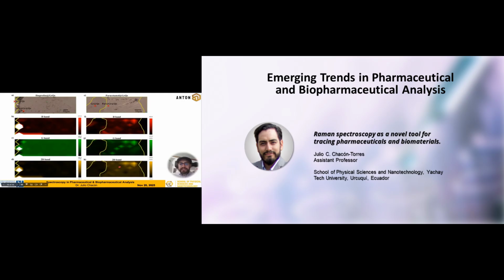But these other areas are way stronger and they have thousands of counts, and we can really say that there is a strong interaction between the molecule of the pharmaceutical and the graphene surface. And that can tell us directly, in an immediate way, that we have a molecule that is coming from our pharmaceutical, because there is nothing else but that, and it's immediately interacting, and there exists a hybridization and molecular interaction between the pharmaceutical molecule and the graphene lattice. It's not being destroyed because the D line is not increasing, but instead it's a kind of functionalization created between the molecules.